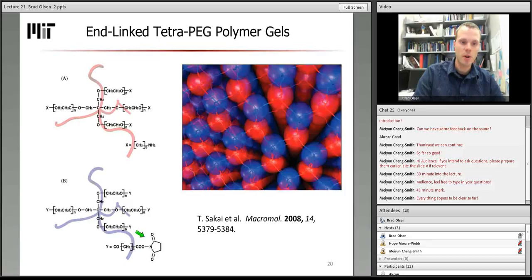This COO, NO2 with 4 carbons right here. The NHS ester group is an activated ester. The ON, the nitrogen, the ON bond makes a relatively labile ester, and so this ester is particularly reactive with amines, which can attack at the carbonyl in order to form a rapid and selective reaction. So what Shibayama's group does is by blending these two molecules together, the two 4-arm stars can only react with one another. Amines can't react with amines, and NHS esters can't react with NHS esters.